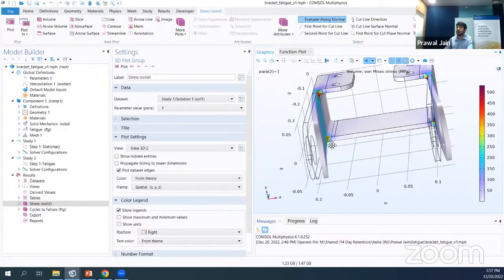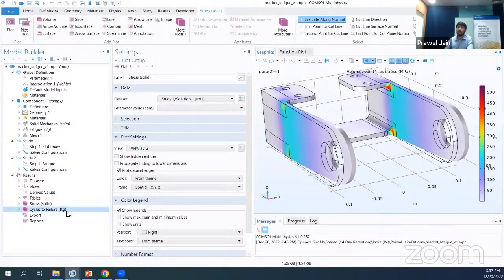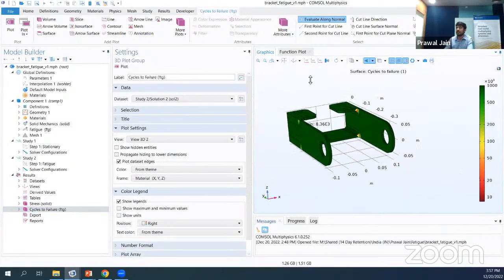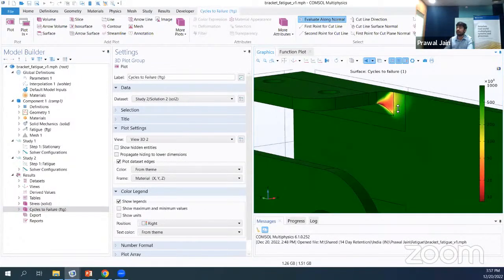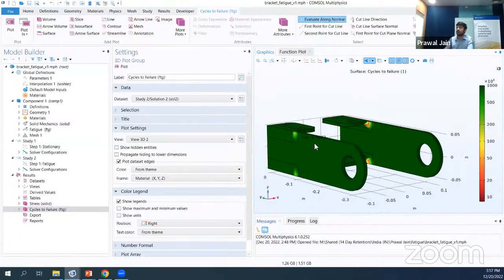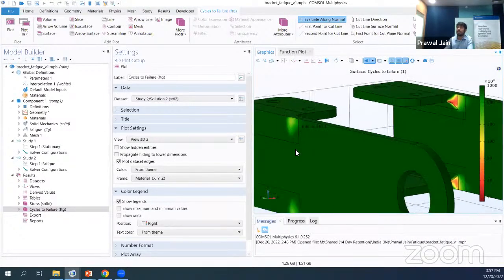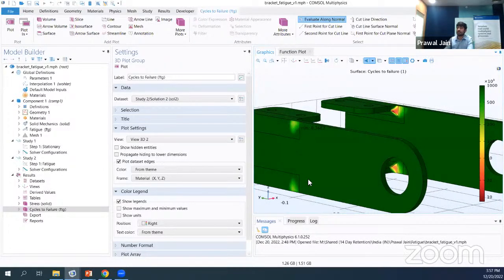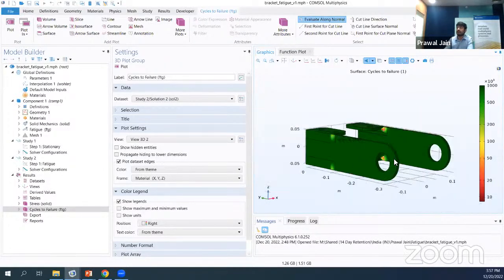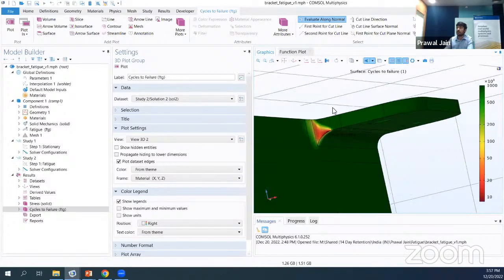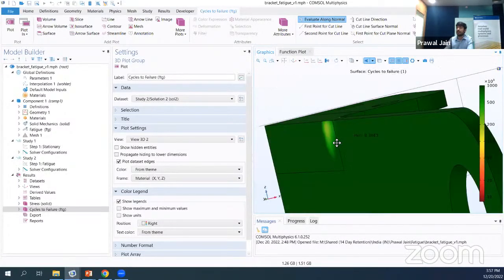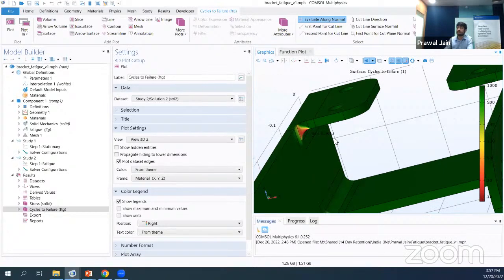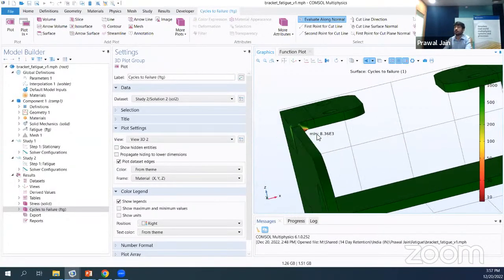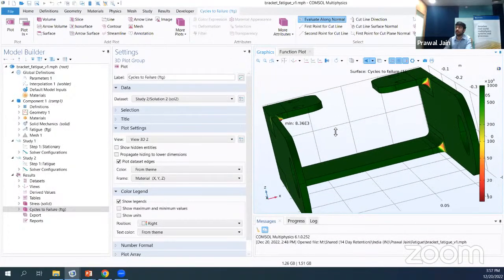So with this, when we accounted for it in the fatigue model, we can see that we were having a minimum life at these sharp corners. And due to stress distribution, we also had this surface having a little bit lesser life than the rest of the component. These sharp corners already failed if we go beyond the stress limits, from which we got the life to failure as 8.36 E3.